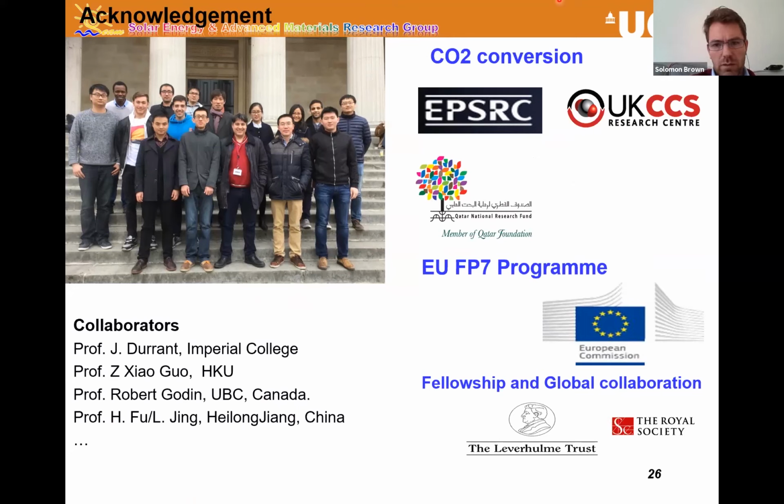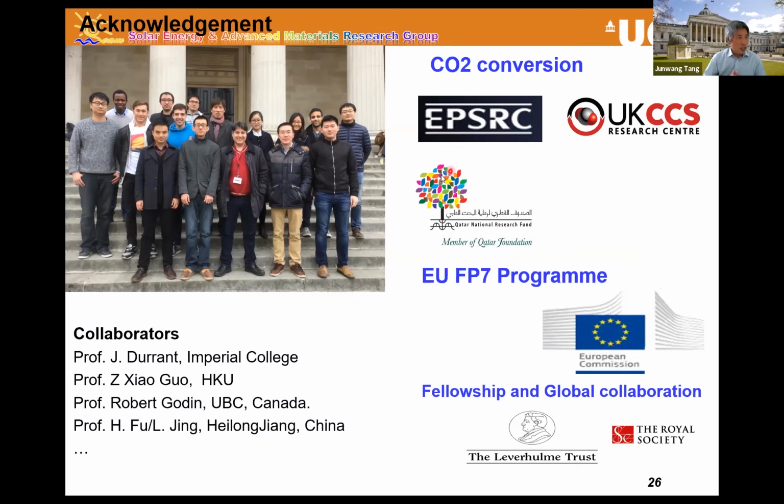What we did, we used urea as a carbon source, and then we added another precursor, I think it's formic acid. The reaction between these two is driven by microwave energy, which is a very fast process. Just mix the two precursors together, put them in the microwave, and switch on the microwave for, I think, about 20 minutes, and the small dots precipitate in the solution. Then we separate that, and that is the microwave carbon dots. Then we load the carbon dots on the carbon nitride by a very simple impregnation method.